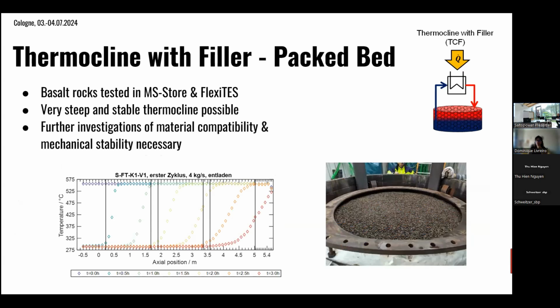Then what we looked at was the thermocline with the filler material. We started off with a packed bed. We had a basalt rock packing in an 8 to 11 millimeter grain size. That was tested in two projects. Here you can see the temperature profiles obtained on the initial charging cycle. And as you can see, there's still a very good thermocline possible. It's a bit wider than if you were having the pure thermocline. The reason is that there's also some heat transfer into the rocks, which is slowing down and widening the thermocline thickness.